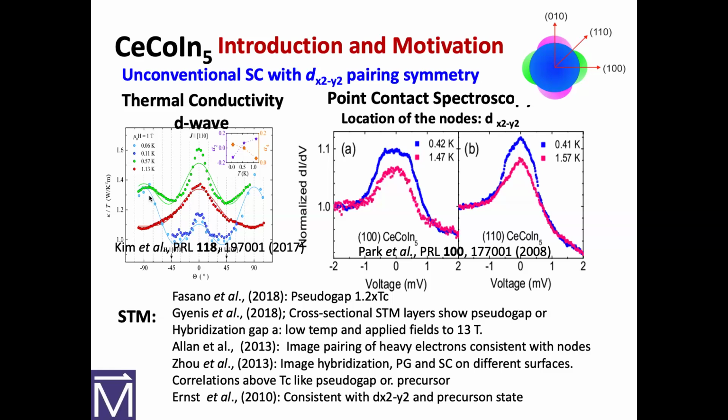So what we're seeing, since there's Zoom here, I don't know if they can see the pointer or not. That's why I have this fancy pointer. But what we see here, we spent a lot of time analyzing this, but that increase in the conductance and the flat top, and sometimes it goes down a little, we can fit that very well to say that is a lobe direction in the order parameter. And if we look at the one on the right, I spent a lot of my adult life studying this stuff, we're injecting electrons into the nodal, the 110 direction.